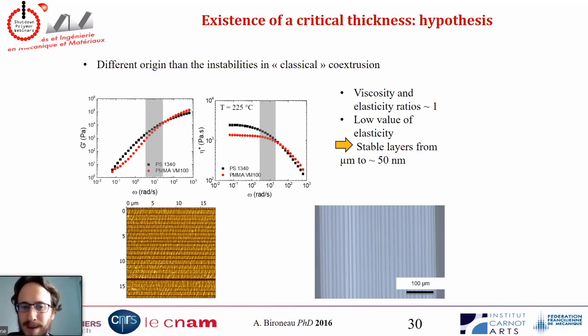But we chose to place ourselves in conditions where we have no such differences in viscoelasticities. So we chose conditions where the two polymers have similar elasticities and viscosities. And the second argument is that we also showed that we are able to reach 50 nanometer continuous layers, whereas when these problems of viscoelasticity occur, you should see some breaking of the layers at about 1 or 10 microns. So because we have continuous layers well below 10 microns, we think that this is not the cause.